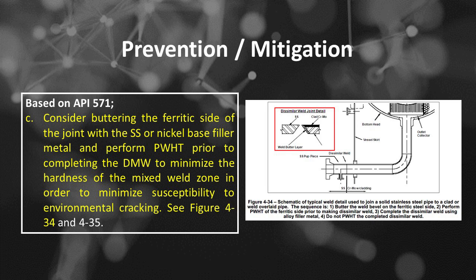See Figure 4.34. Schematic of typical weld detail used to join a solid stainless steel pipe to a clad or weld overlaid pipe. The sequence is: 1. Butter the weld bevel on the ferritic steel side. 2. Perform PWHT of the ferritic side prior to making dissimilar weld. 3. Complete the dissimilar weld using alloy filler metal. 4. Do not PWHT the completed dissimilar weld.